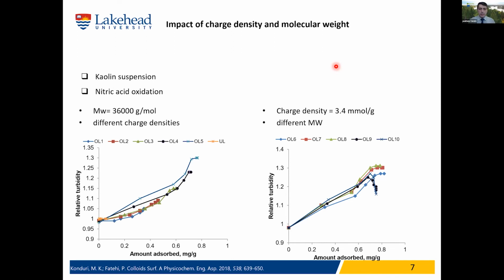In this set of experiments, we generated 10 different samples. One batch had similar molecular weight but different charge density. Another batch, which is on the right side, had different molecular weight but the same charge density. Of course, we had many different reactions, but this is how we categorized the products of this oxidation reaction. We had 10 different samples plus the unmodified lignin, and then we applied different dosages of each one to clay and studied its dispersion, or basically the relative turbidity of the suspension. Relative turbidity is an indicator of the dispersion of the sample.